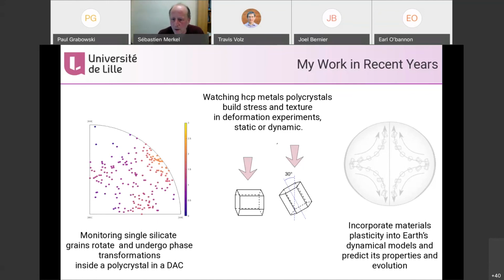So for the first question on HCP iron, we did not see any evidence of BCC iron in the diffraction data. It's HCP everywhere. We see BCC on release, actually sometimes FCC, sometimes BCC, but I don't see any high pressure BCC. I see HCP. Now, for the question of Chase,